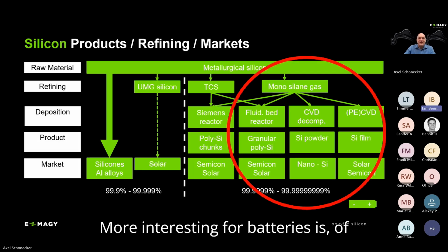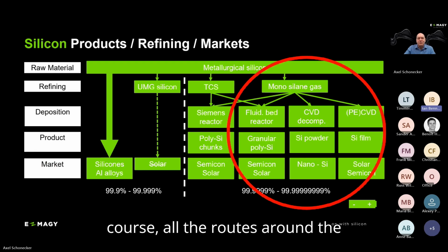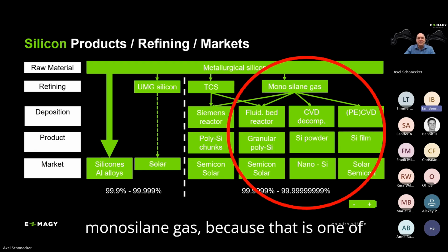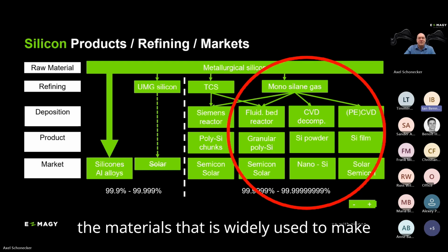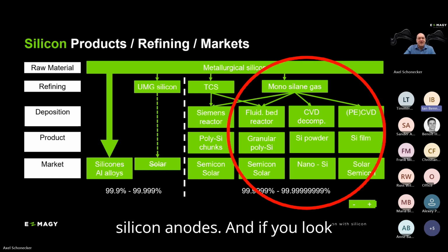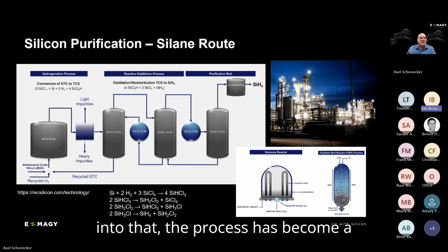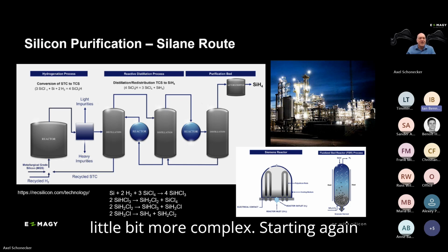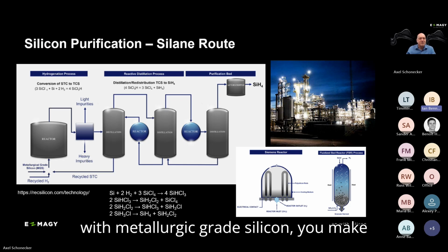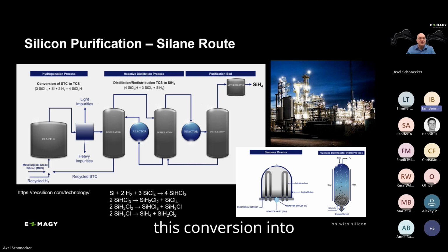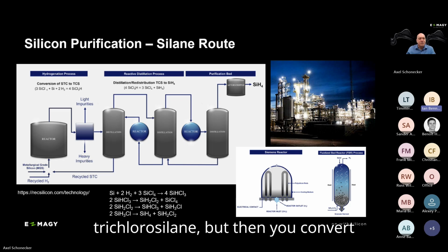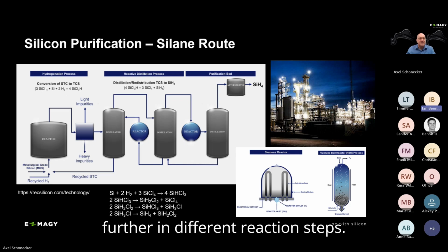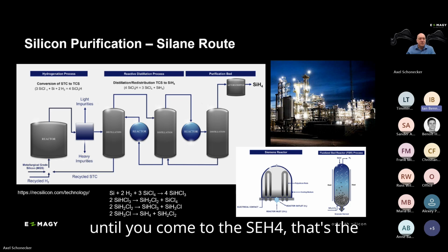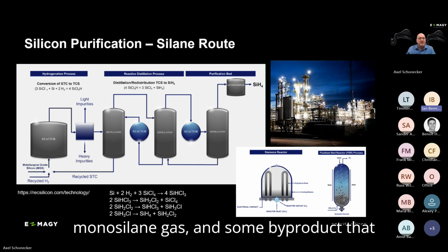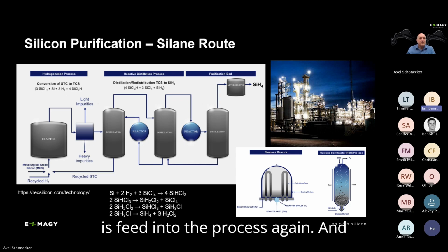More interesting for batteries is, of course, all the routes around the monosilane gas, because that is one of the materials that is widely used to make silicon anodes. And if we look into that, the processes become a little bit more complex. Starting again with metallurgical grade silicon, you make this conversion into trichlorosilane, but then you convert further in different reaction steps till you come to the SiH4, that's the monosilane gas, and some byproduct that is fed into the process again.